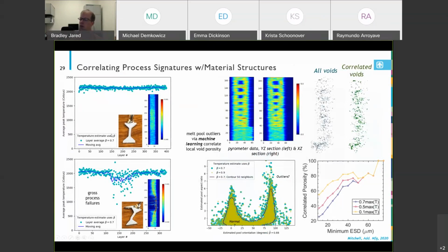We've also shown that when we use this pyrometry data, we can find deformation defects in the part, right? So this is pretty obvious when this comes off the machine, that this part failed here on the bottom left. But really what you could do is start monitoring these, and you can say, hey, I've got a problem, I need to correct something. I may have to stop the build or maybe change the build or whatever. So it shows you at least a path forward to possibly doing either local or even global process control on your machine to improve the performance of the material and what's happening.